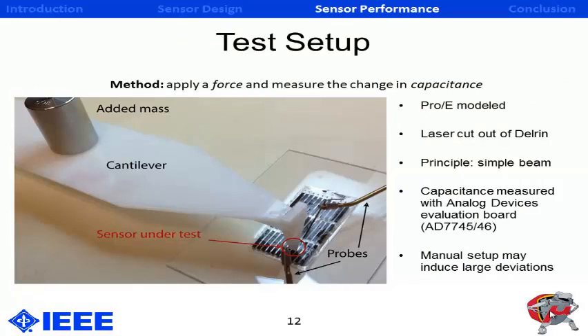For the test setup, the method was very simple. It's to apply a force and measure the change in capacitance. In this case, a cantilever beam was fabricated, modeled in Pro-E and then laser cut out of Delrin. And the principle is simple. We apply a mass at the center of the beam, and then half of the weight is transferred to the probe tip. Capacitance is then measured using an Analog Devices evaluation board.